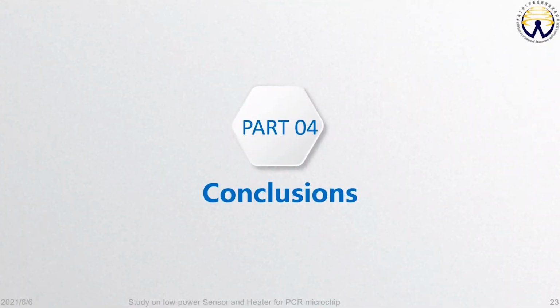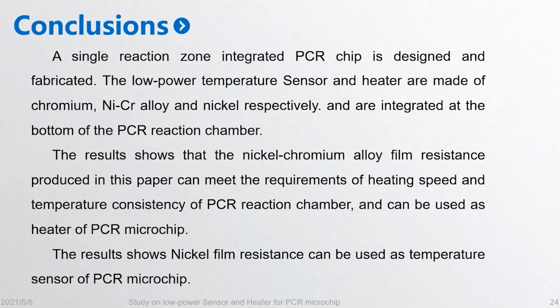Okay, now let's go to the last part of our presentation, the conclusions. A single reaction zone integrated PCR chip is designed and fabricated. The low-power temperature sensor and heater are made of chromium, nickel, chromium alloy, and nickel respectively, and are integrated at the bottom of the PCR reaction chamber. The results show that the nickel-chromium alloy film resistance produced in this paper can meet the requirements of heating speed and temperature consistency of PCR reaction chamber, and can be used as heater of PCR microchip. The results show nickel film resistance can be used as temperature sensor of PCR microchip.